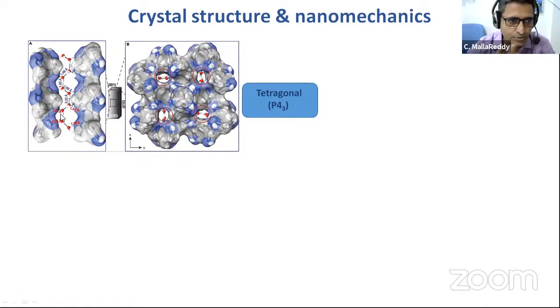If you look at this crystal structure, you have a polar water chain, and all these bonds are actually aligned in one direction when you look at the polarity of the bonds. So it is basically a polar hydrogen bonding chain, and then you have these bipyrazole molecules which are connected to this network from both sides, and these water molecules are sitting in a channel. All of them are going in one direction. So they are all polar, the polar direction is along the needle direction, and all the dipoles are aligned in one direction. So it is a tetragonal crystal, a polar space group. So this is actually a piezoelectric space group.